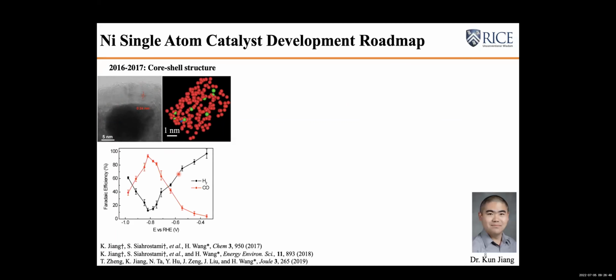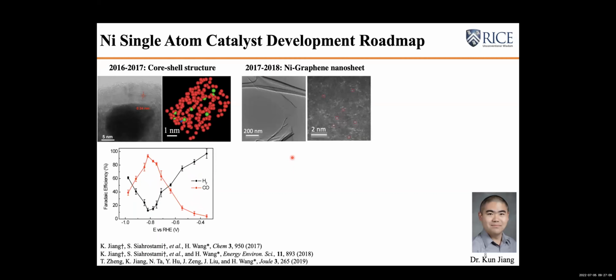As we can see from the catalytic performance, the CO Faradaic efficiency continues to ramp up to about 80 to 90% while suppressing the competing hydrogen evolution reaction to only 10% or so. So this was the very first version of our journey. And then for the second version, we were thinking in a different way. We know that because the surface nickel dopants are the active site.